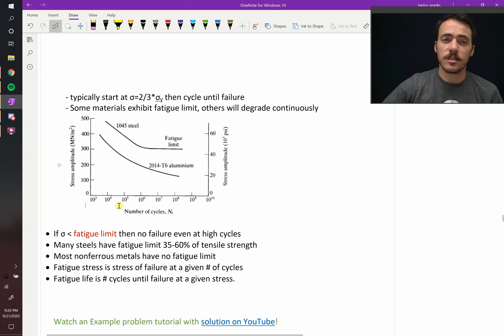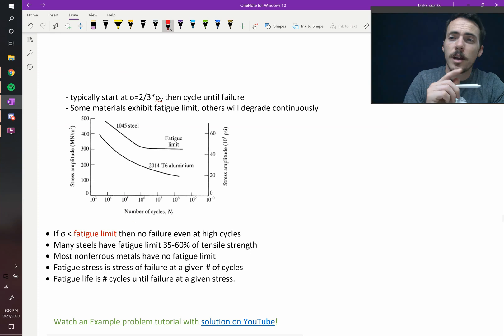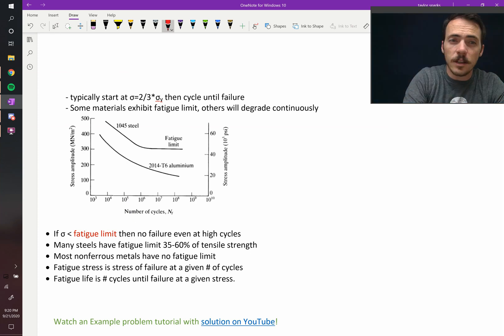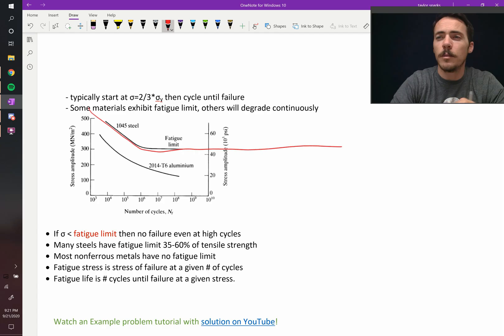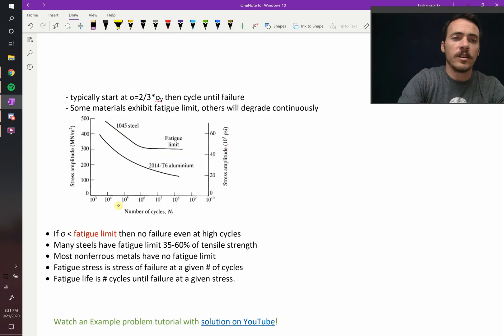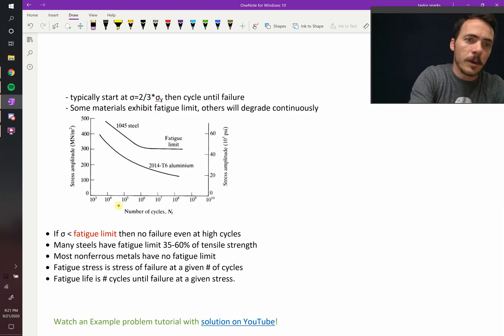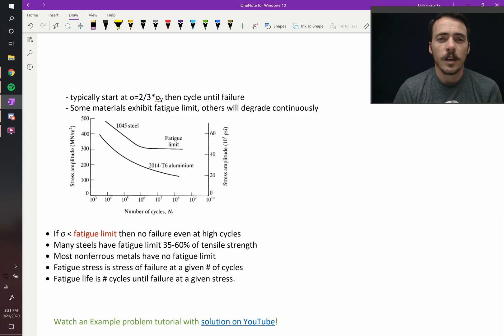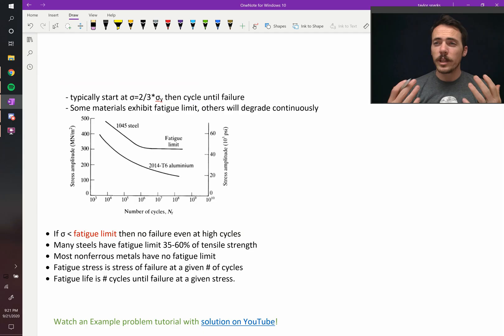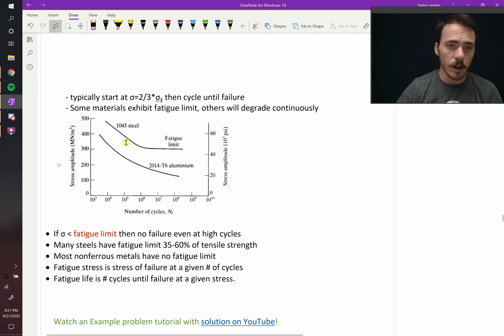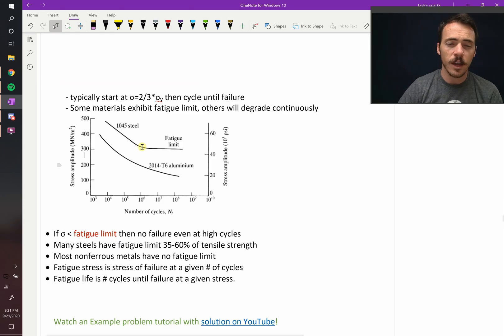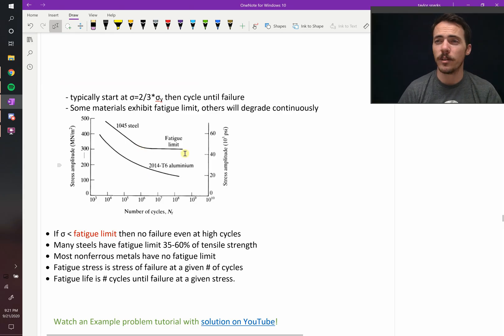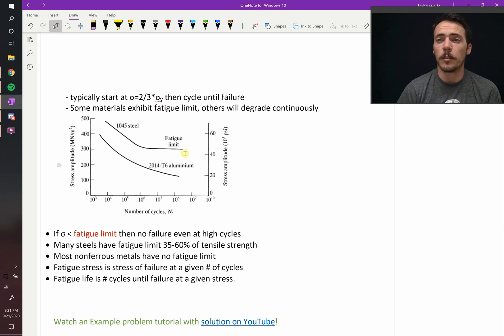Now, some materials exhibit a really cool property. They get weaker to a point, a limit, and then they stop getting weaker. They exhibit what's called a fatigue limit. In this case, 1045 steel has a fatigue limit of around 300 mega newtons per meter squared. It doesn't get weaker than that. Which is really awesome if you're designing for something that needs to last millions of cycles. Because it gets weaker up until about 1 million cycles, 10 to the 6 cycles. And after that, it has a minimum strength that you can count on it maintaining. That's really valuable for long-term applications. It gives you something to design around.